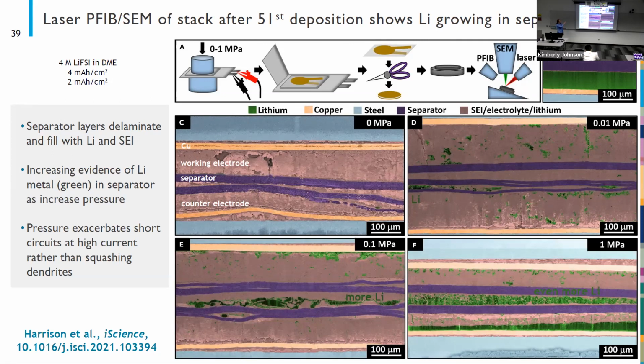Yeah, so we did all of this in pouch cells so that we could control the pressure better, and then we took them out and put them in coin cells. And we used about 100 kilopascals of pressure in the coin cell, but we don't think that changed much at that point. The damage was sort of already done by the original experiments.